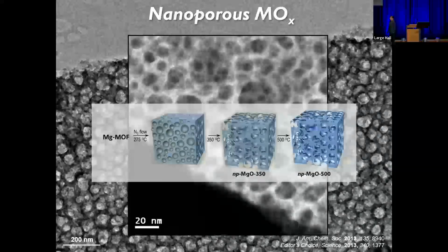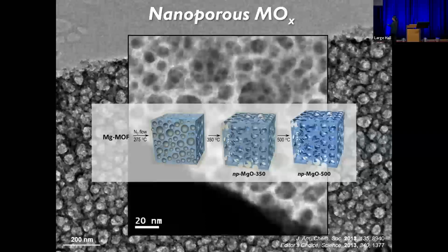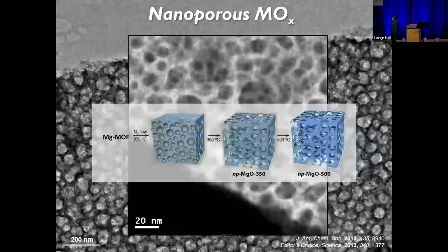So in this case, we use the aliphatic ligand instead of aromatic ligand, and then we can prepare the thermally unstable metal organic framework. And from the synthesis, we realized that this aliphatic ligand, in this case adipate, is decomposed at low temperature to form the organic vesicle. And this organic vesicle acts as a porogen. And at higher temperature, this organic vesicle is evaporated. Then we can obtain the hierarchically porous metal oxide.